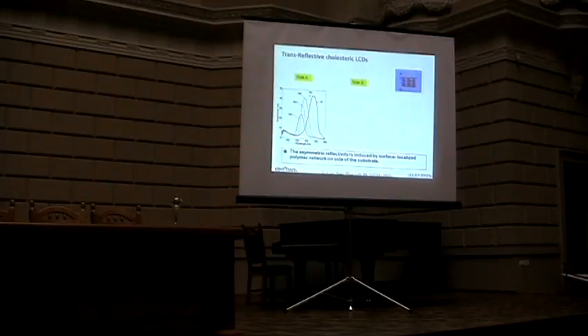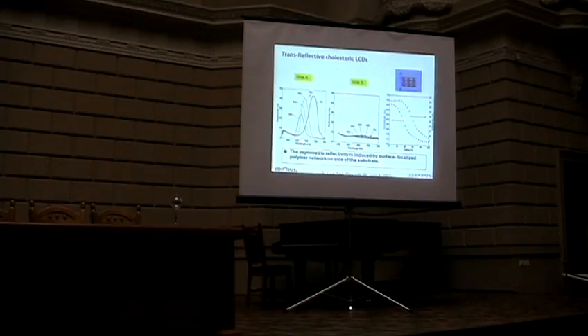On the other hand, if you put in some thin layers of polymer, like what I just showed you, they phase separate and localize on one layer, so not too much in the bulk between the two substrates. In this case, you're able to apply the field a little bit higher, and the Bragg reflection wavelengths can be shifted a little bit wider before it totally unwinds. But it's kind of interesting if you compare putting polymer in the bulk to putting polymer on one substrate surface. Here you see anisotropic reflection and transmission on one substrate, while the other doesn't reflect the light. And certainly the Bragg reflection wavelength and reflectivity are a function of applied voltage in this case.